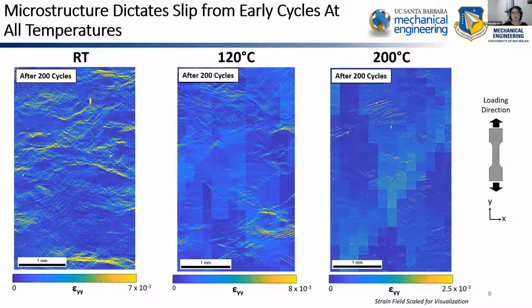You are correct about the shear strain. When actually determining and finding those slip traces, we used all three strain components, and those slip traces are going to exist as discontinuities in the field. So we did use all three to find those discontinuities and extract them for all of our analysis. The Y is where we had the largest amount of strain.